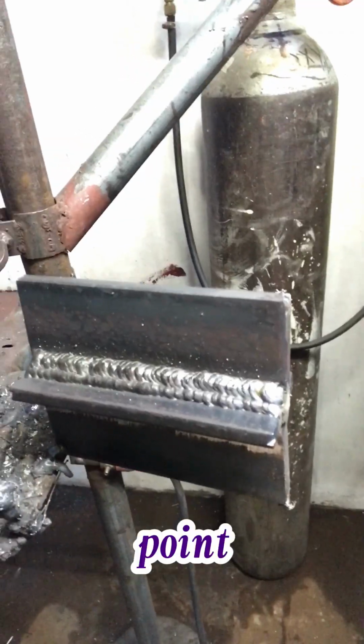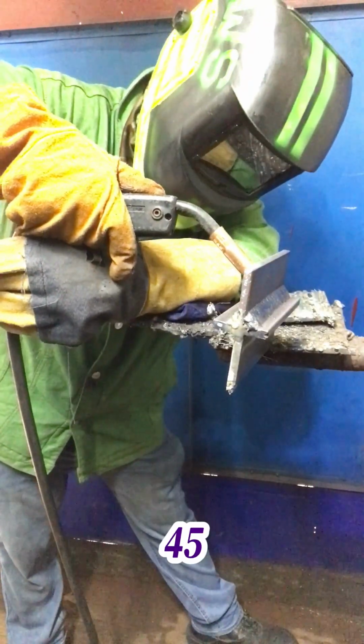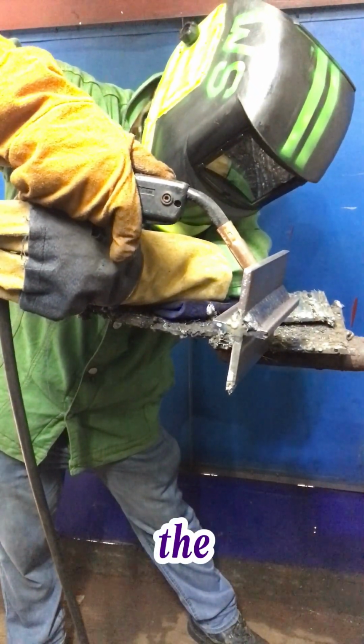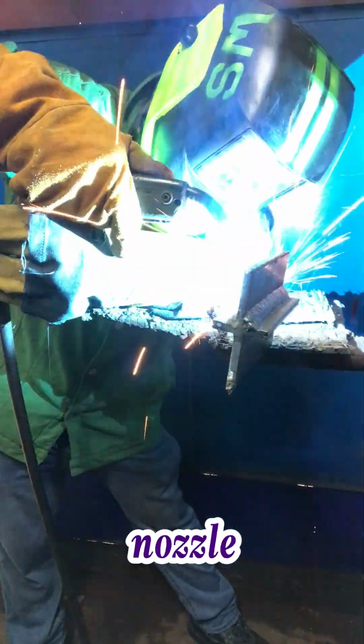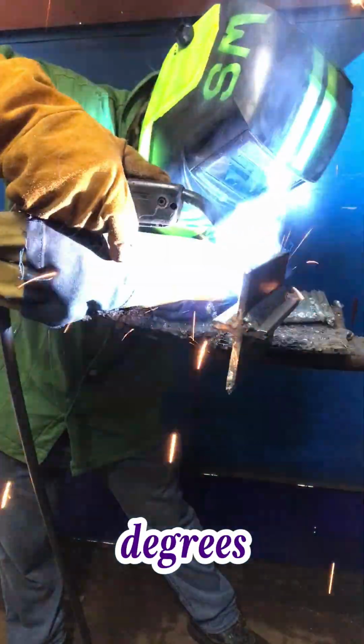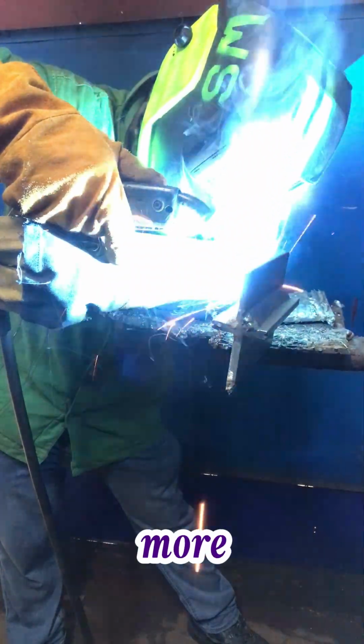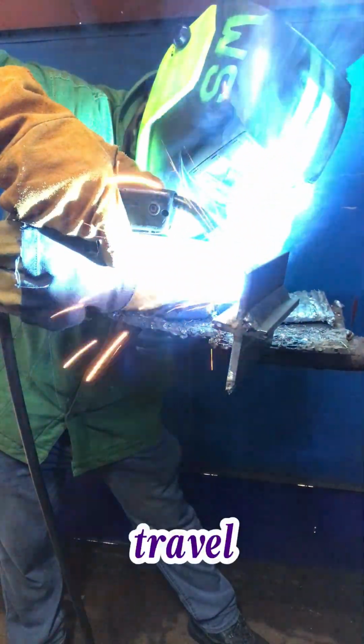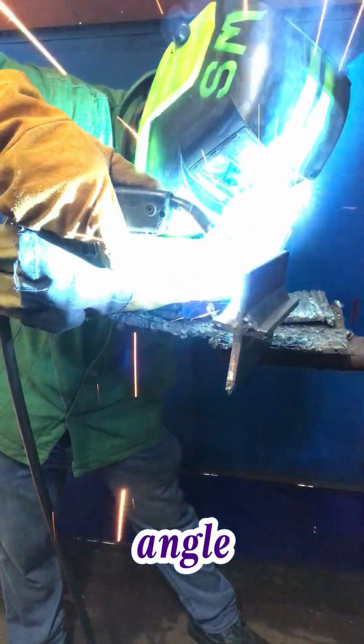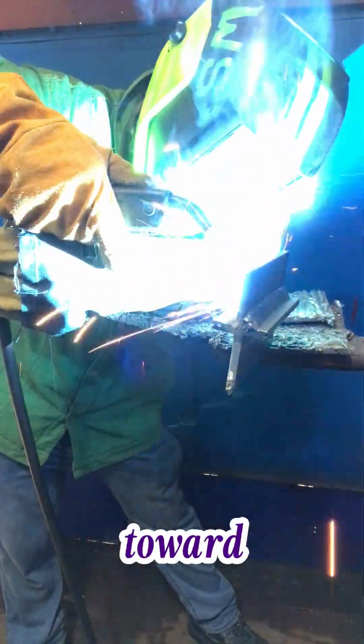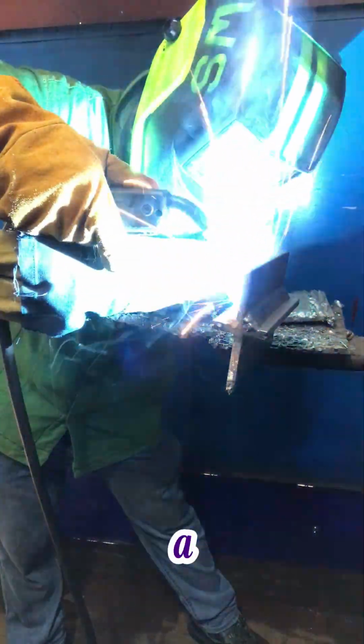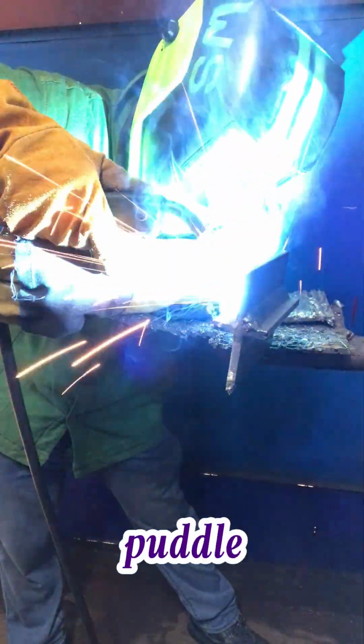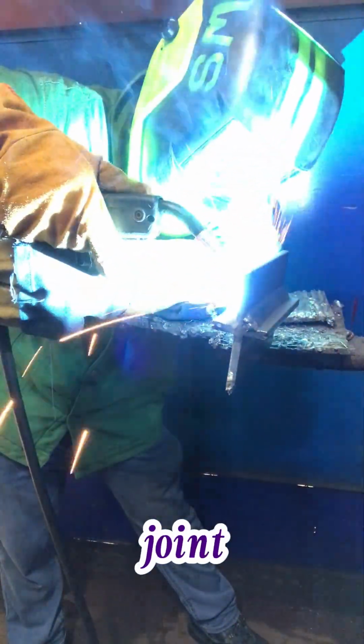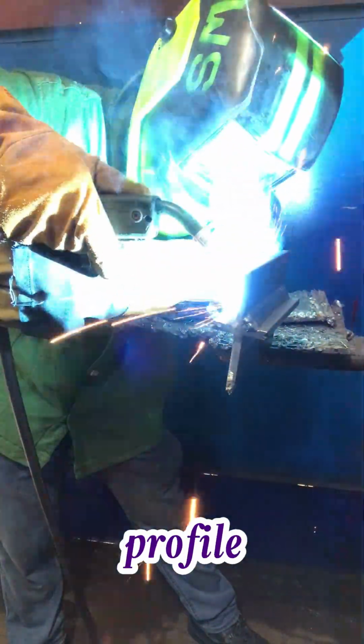Your physical stance and gun angle determine where the heat goes. Work angle 45 degrees. Point the gun directly into the root corner at 45 degrees. Because gravity pulls the puddle down toward the bottom plate, tilt the nozzle slightly higher, around 40 to 45 degrees relative to the bottom plate, to direct slightly more heat into the vertical wall. Travel angle 10 to 15 push angle. Lean the gun 10 to 15 degrees toward your direction of travel. Using a push technique keeps the arc at the leading edge of the puddle, giving you clear visibility of the root joint and producing a flatter, cleaner bead profile.